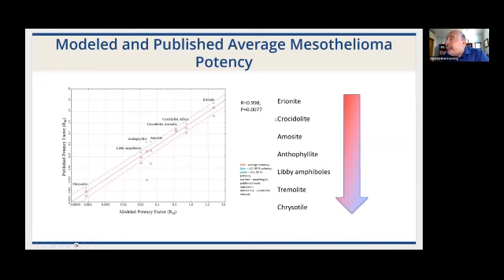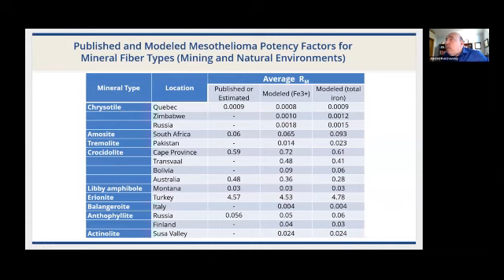And we can look at that and we can see that the correlation is very high. It's 0.998. It's a very high statistical level of significance. And this is now the scale we can use. I would like to repeat, it's probably the 4th time, chrysotile is here down below. It doesn't mean that it's not carcinogenic, but it shows that different fibers have different potency, propensity, carcinogenic quality to harm humans at different levels of exposure. This is from our paper, published modeled mesothelioma potency factors. And you see how well technically our model works.